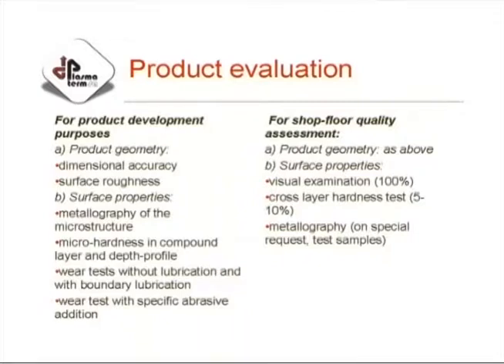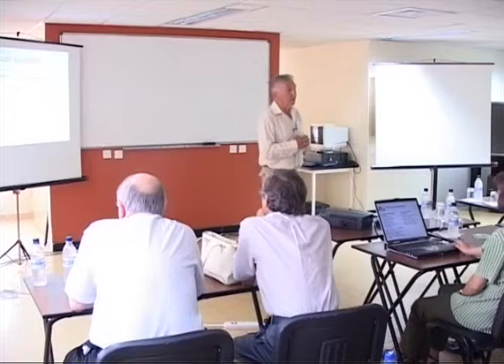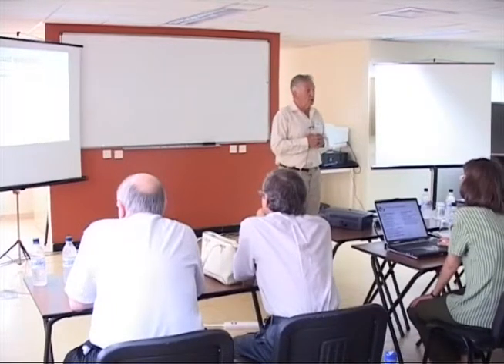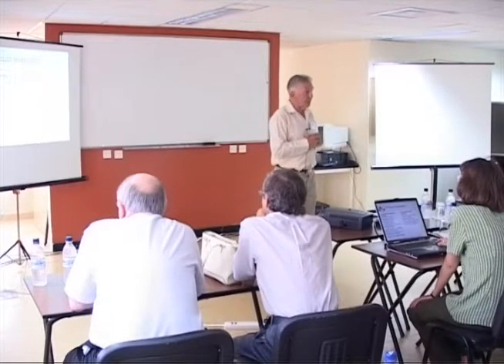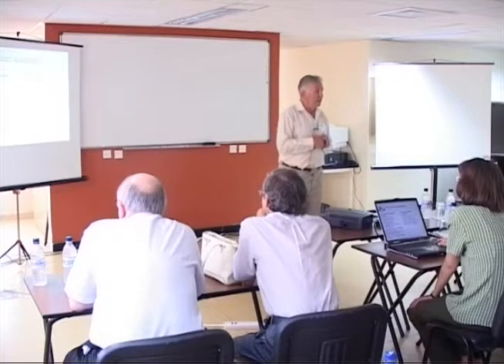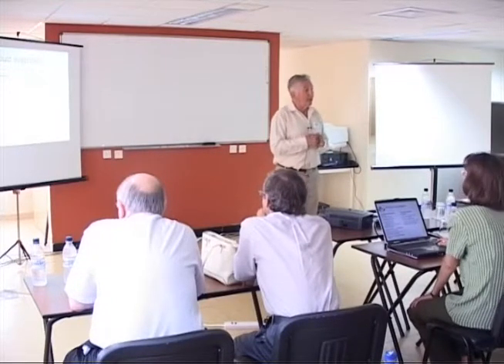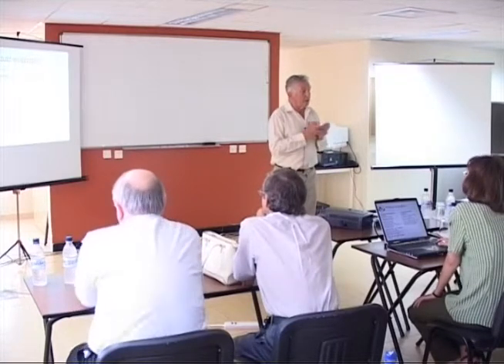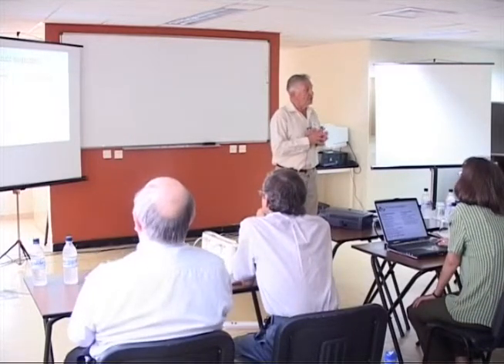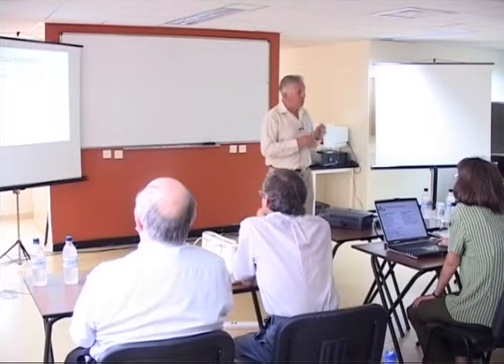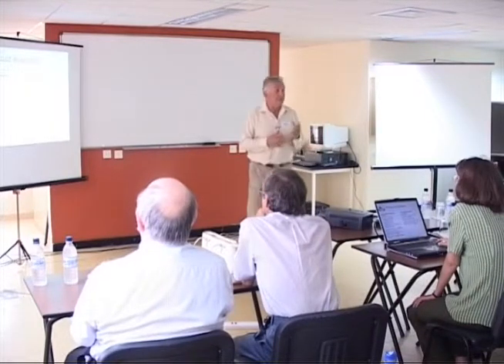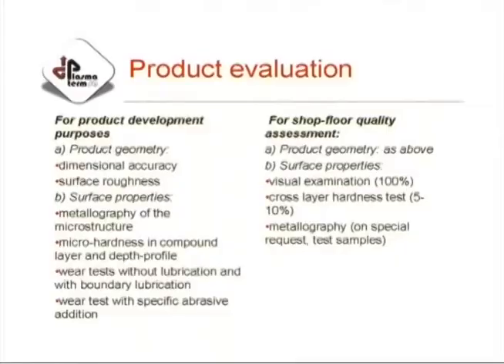We have quite a range of possibilities to test the wear properties of the surface using a kind of Falex machine, which we developed ourselves to match exactly our needs. And we are also able to measure rather accurately the coefficient of friction of the surfaces, which also gives a very important indication. But certainly, this is a rather complicated test system, which should cost a considerable amount of money. And that's for shop floor quality assessment.